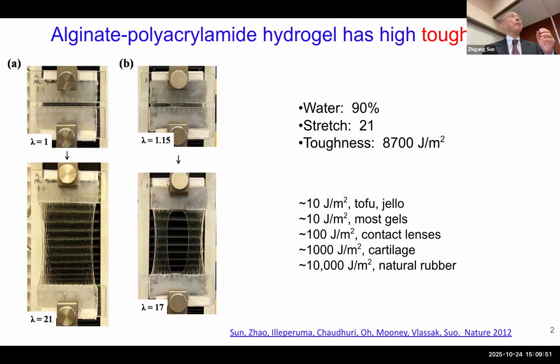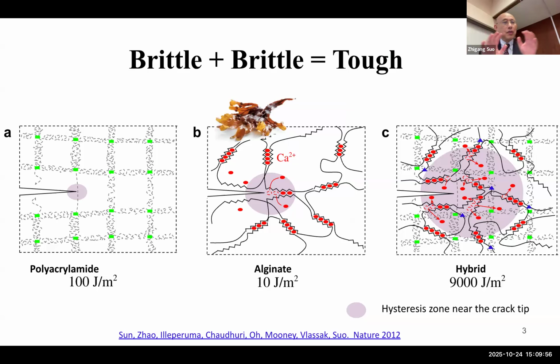Now, we were very embarrassed by this paper as well. So there is no flaw, no fraud, anything. It's just that some property is not actually very good, we later found out. So first, about the goodness of this paper. This paper is made of, as we said, polyacrylamide. Polyacrylamide itself is a hydrogel with a polymer network with a lot of water in between. And the toughness is 100 joules per meter squared. This is the material. And then there's alginate.